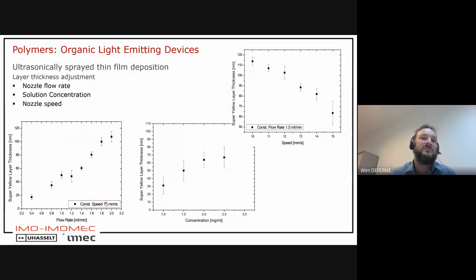If we have a constant speed, so the movement of the nozzle over the substrate, of 15 millimeters per second. So that's also something that we investigated here, taking a constant flow of 1.5 milliliters per minute. What is the optimal speed? And then you see you go to 14 to 15 millimeters per second for a layer thickness of 80 nanometers. And then finally, the layer thickness as a function of the concentration. So what concentrations do we need? And you see we go up.